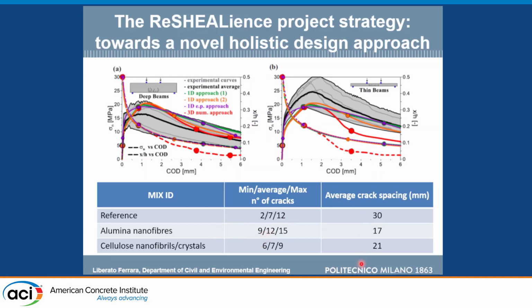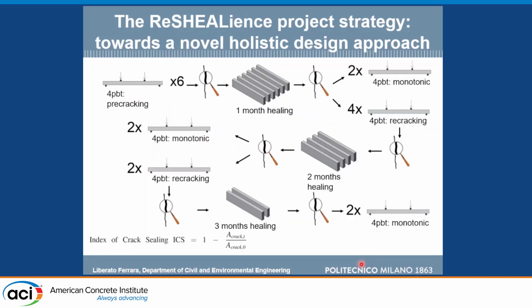So this was the strengthening at the very molecular level, I would say, which allowed us to obtain very, very narrow cracks. So then we wanted to explore, as I said, the durability and the self-healing capacity. So what we did with the specimens, we pre-cracked them up to the service design level.